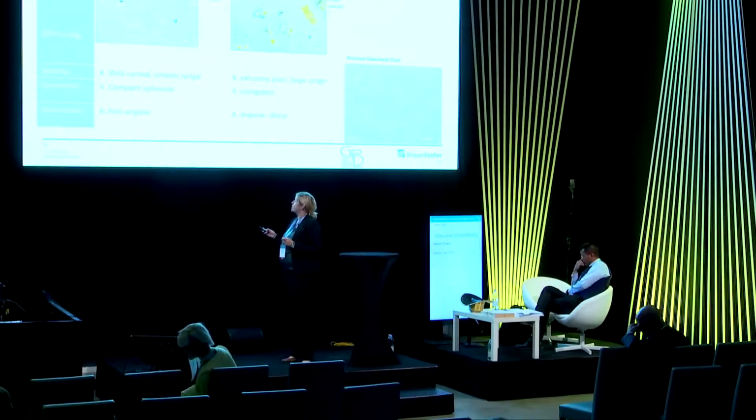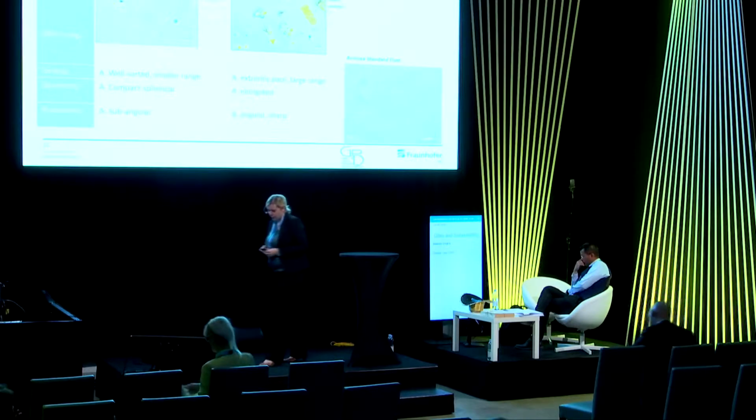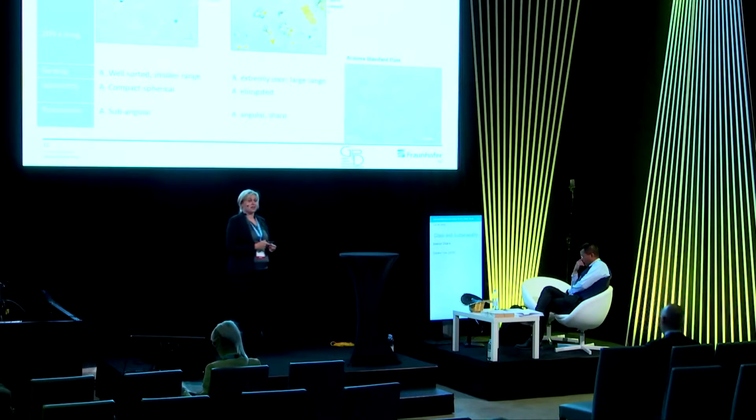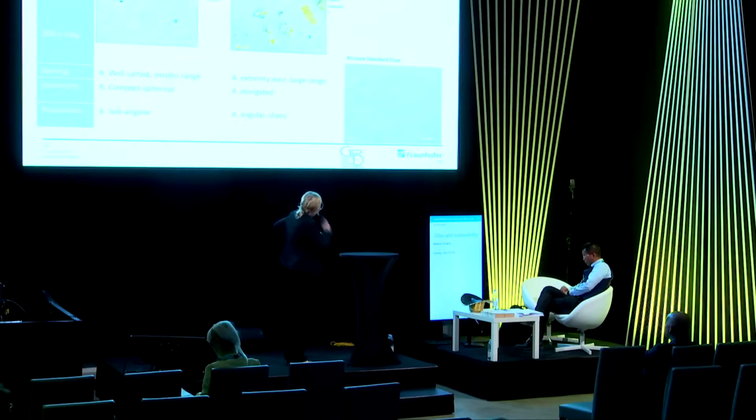And you can see here it has still edges, it's subangular, but this is really angular and sharp. In comparison, if you want to do some soiling test, I want to know what the surface is doing with the dust, or the dust is doing with the surface, a major part of the soiling community is doing that with the Arizona standard dust. This is a magnification of 100, but you can still see it's so much smaller, it has fibers, it does behave different.